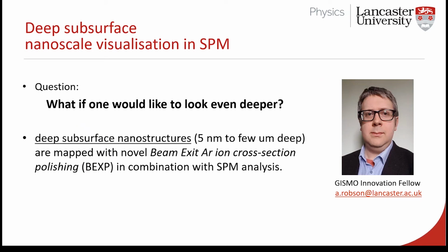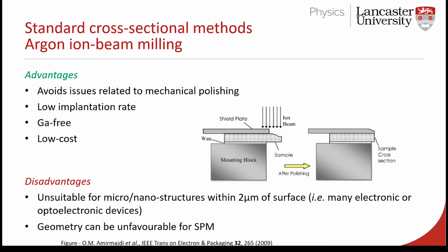And so if anybody's familiar with focused ion beam milling, FIB, which is used a lot with TEM, transmission electron microscopy, for example, this is a technique that can give you a huge amount of information about very thin subsurface structures. The problem with that is it tends to be very expensive. It's very, very good, but it's very, very expensive, and it's quite slow.